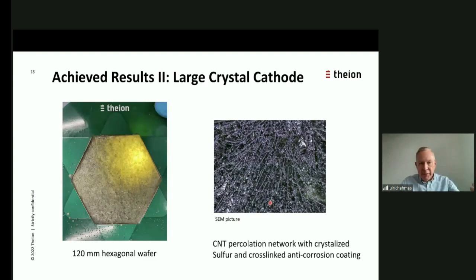The next step will be that we build larger cells, pouch cells now, with a higher energy, with higher ampere hours. Therefore, we built in summer a larger wafer of 120 millimeter length. And you see here the microscope picture, the carbon nanotubes percolation network linked together like nanowires, and around it is the crystal of the sulfur.